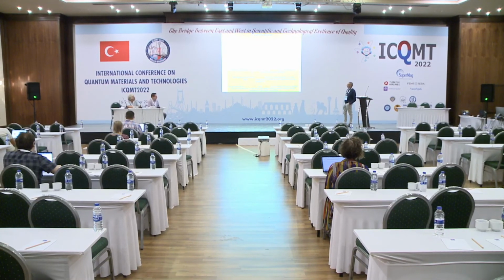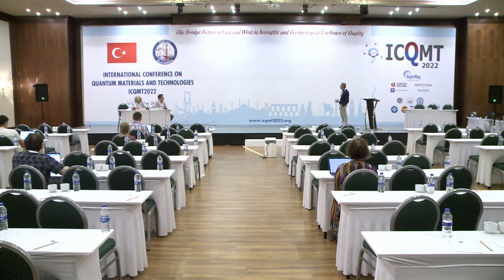No, but the question is, how do you estimate the time scales? 5 picoseconds, 20 picoseconds. How do you do that? From the Larkin-Ovchinnikov, yes. I measured the critical velocity, and from that formula I get it. And I said that, of course, there are completely different mechanisms, whatever, but the scaling between these two times is quite robust, at least in our experience.